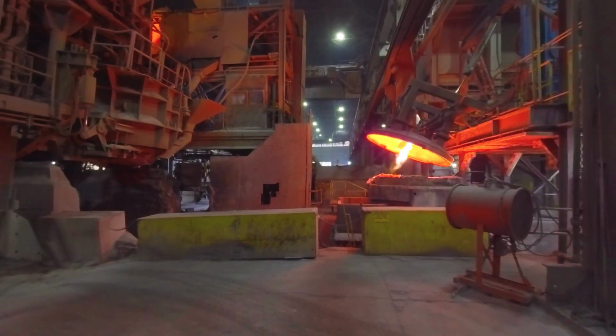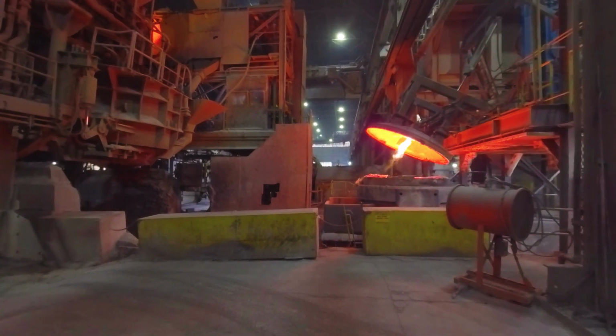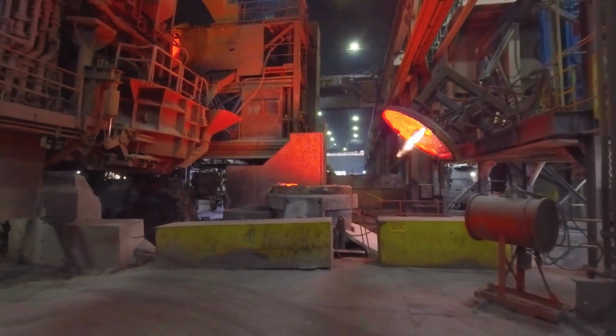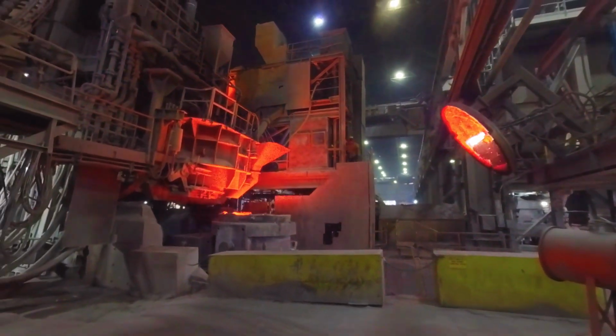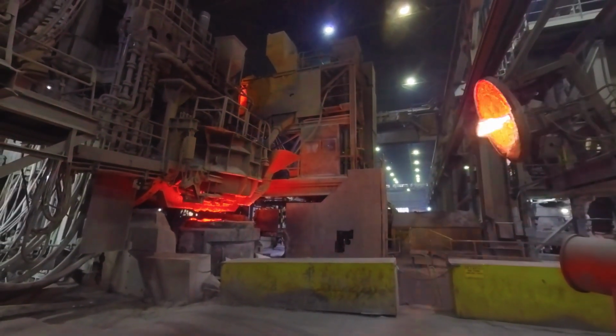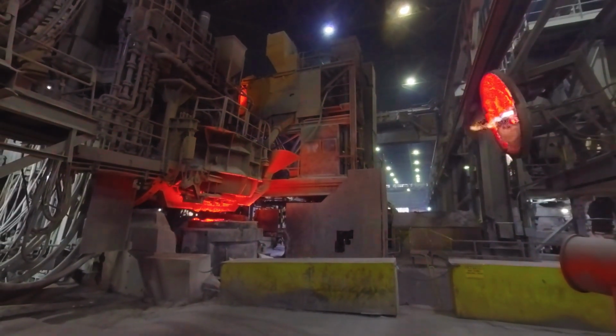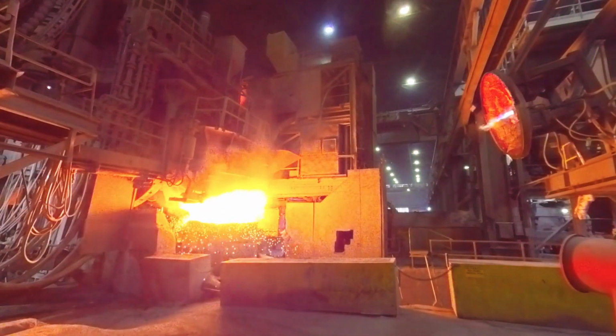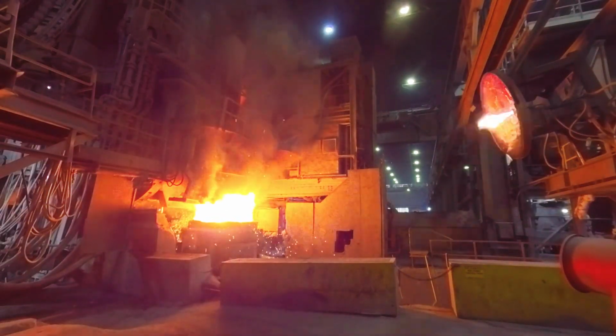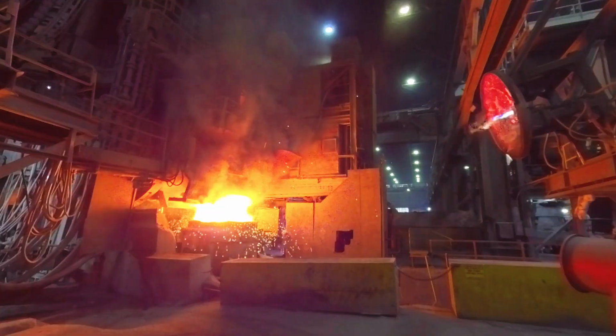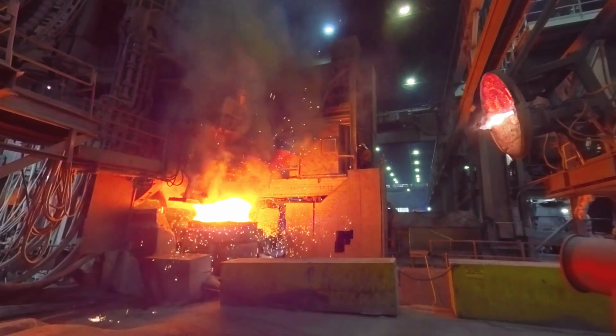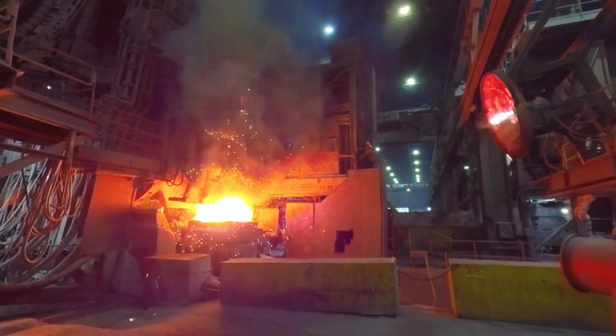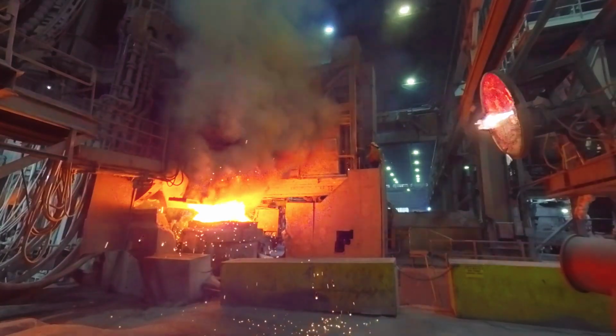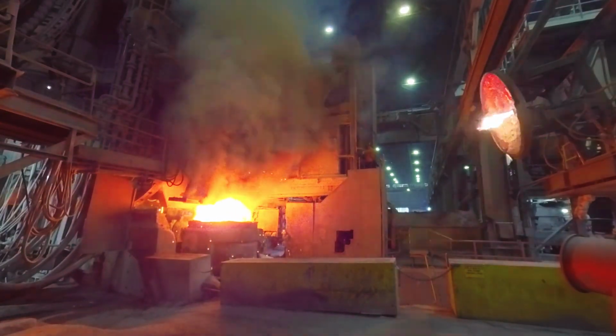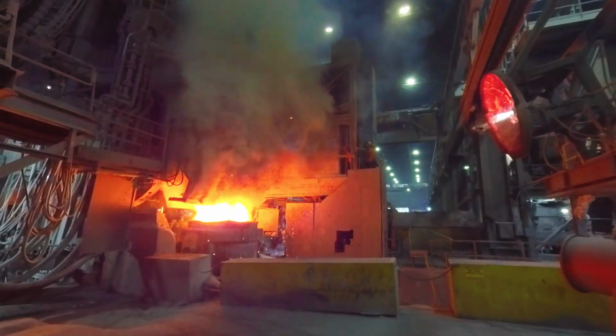The ladle is moved into position beneath the furnace, and the roof of the preheater swings open to receive it. Then, the furnace begins to tilt. Molten steel flows out from the bottom of the furnace into the ladle. As it pours, alloys are added along with materials like lime to refine the final chemistry of the steel. Each heat transfers roughly 47 to 50 tons of molten metal into the ladle.